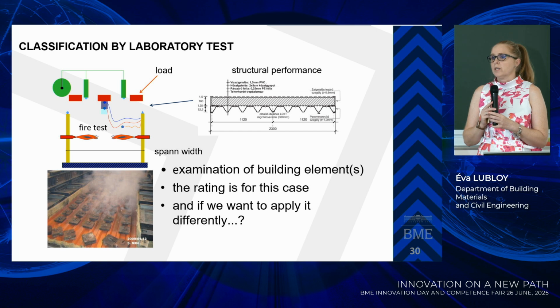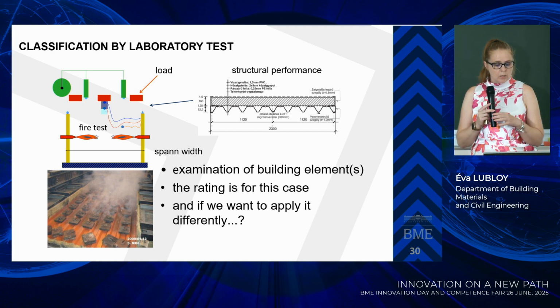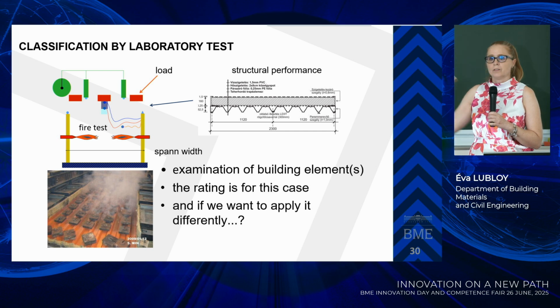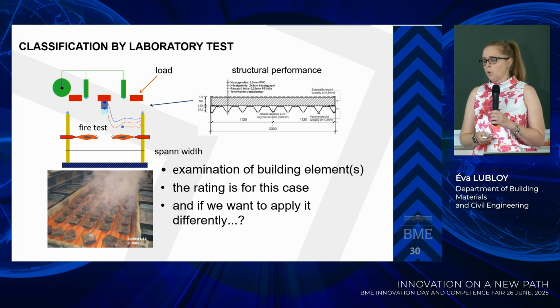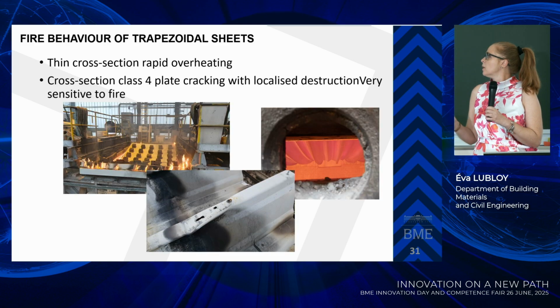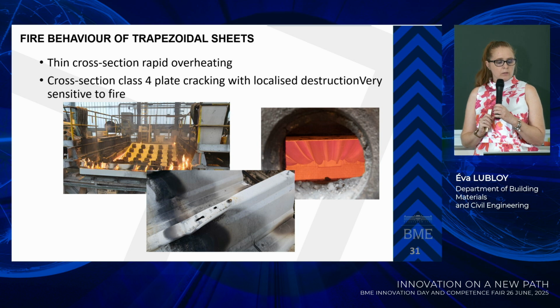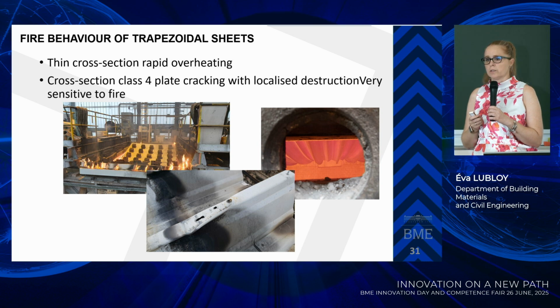Yeah, how can we make testing of the structures? We put it in a furnace, we loaded it, and we measured the deflection and the temperature. If we see, then this cross section could overheat rapidly, and they are very sensitive to fire. We have made more than 20 fire tests, and from this we have developed calculation software special for trapezoid sheets.